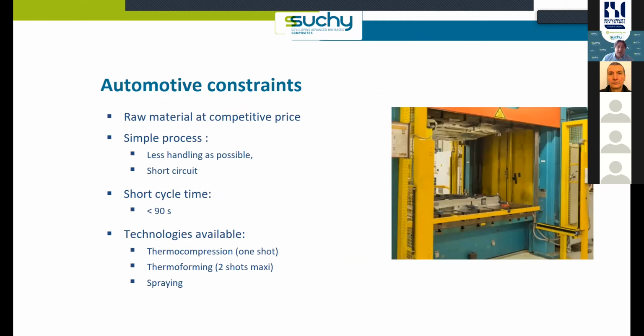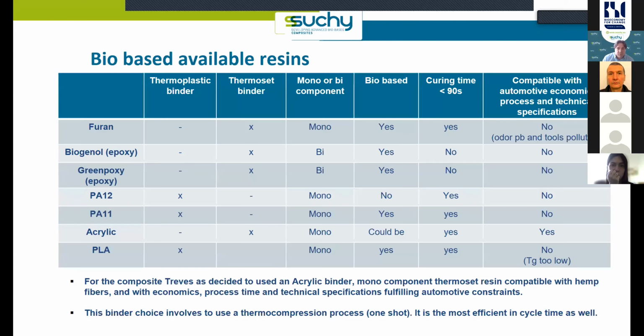So our automotive constraints are very special, because we are using processes with as little handling as possible, short circuit. We have extremely short cycle time. Here I write 90 seconds. Most of the time it's more 60 seconds that we are actually asking for our processes. So it has to be extremely fast. And most of the time we are using thermocompression, thermoforming, depends. And the way we are impregnating our products is definitely a very simple one. It's spraying. And spraying is really not the best way to do such a composite. So we are putting constraints on one another: short cycle time, unusual impregnation techniques, and simple thermocompression afterwards. So we are not in an easy world.